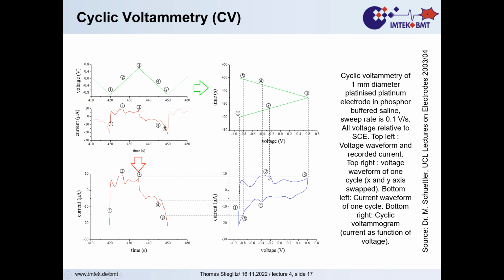If the voltage is increased, they occur at a certain potential, and if we reverse that, we see that the reversed reactions occur at different spots, or other reactions occur there. We know where the water window is when the current goes up steeply. Then we go probably a little bit back, so that we do not come into that irreversible reaction. It might be suspicious that we have minus 0.9 and plus 0.6-something volts there; it's because this has been done versus SCE.